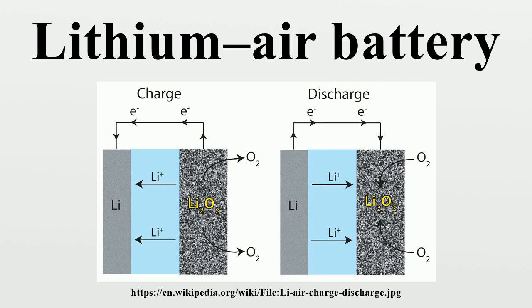Upon charging and discharging in aprotic cells, layers of lithium salts precipitate onto the anode, eventually covering it and creating a barrier between the lithium and electrolyte. This barrier initially prevents corrosion, but eventually inhibits the reaction kinetics between the anode and the electrolyte. This chemical change of the solid electrolyte interface results in varying chemical composition across the surface, causing the current to vary from point to point. The uneven current distribution furthers branching dendrite growth and typically leads to a short circuit between the anode and cathode.